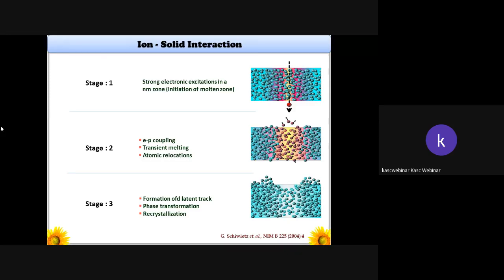In step 2, further it may be irradiated. Then the electron-phonon coupling usually takes place. Due to the electron-phonon coupling, the energy transferred through the trajectory, or the path of a material, can be transferred over the rest of the zone of the material, and it can cause transient melting, and atomic relocations are also possible. And at last, the formation of latent tracks. Latent tracks are nothing but the amorphous region inside the material. And during this amorphization, there may be a possible chance of phase transformation and recrystallization.